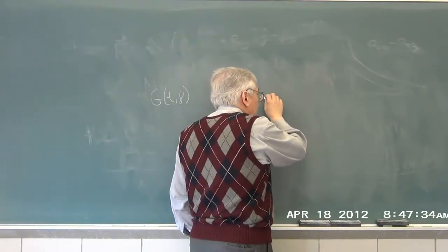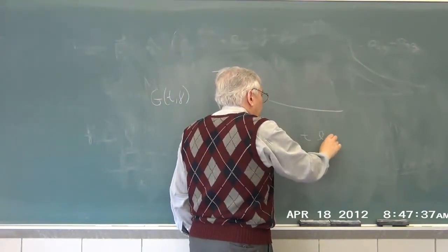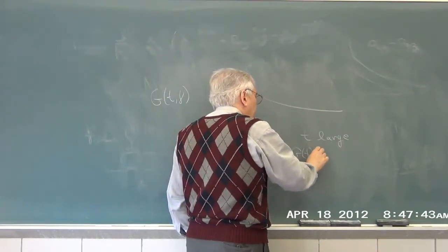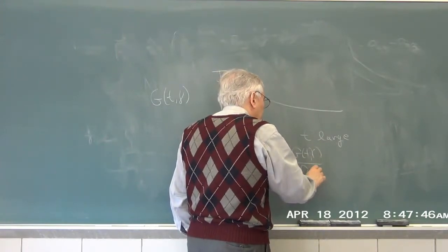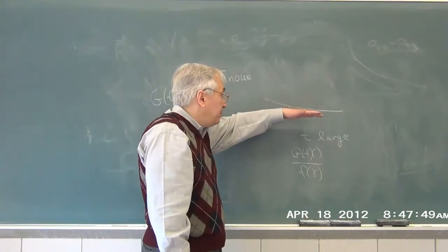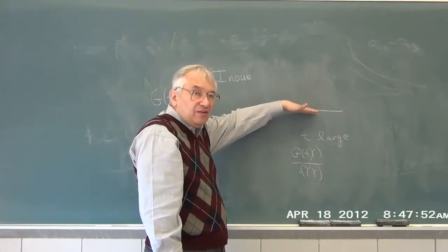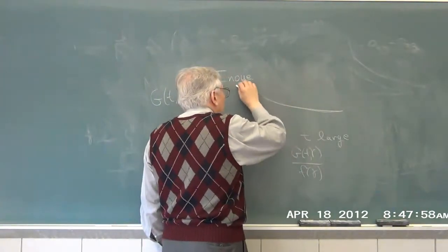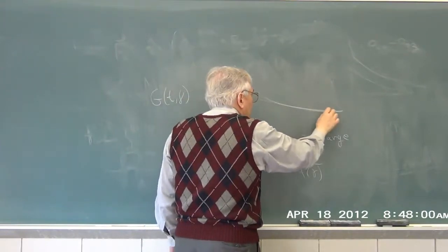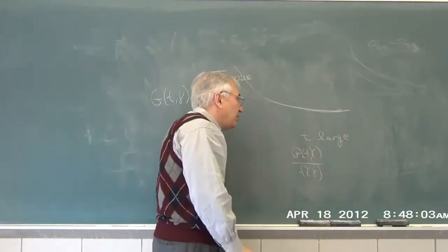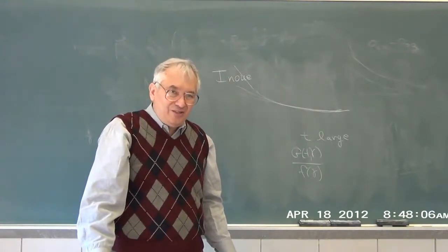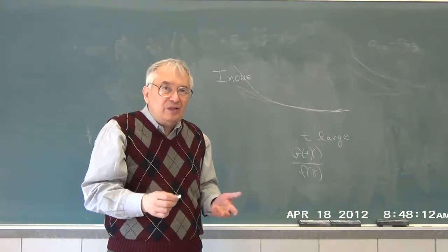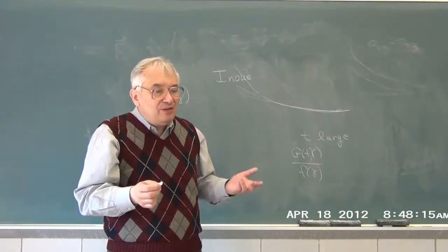And what Wang and collaborators do, there's a nice paper, they show if you look out at large times and you take g of t and gamma over some function of gamma, that is, if you multiply the curves by some constant, at small time the curves may be different, but at large time, if you multiply the curves by gamma, the curves all lie on top of each other. And therefore, at long time, the assertion is a common relaxational process, which some people claim they know.